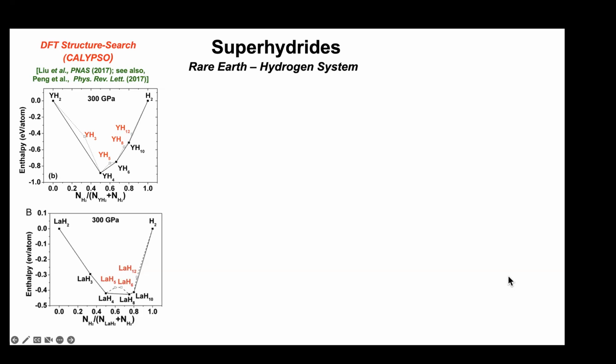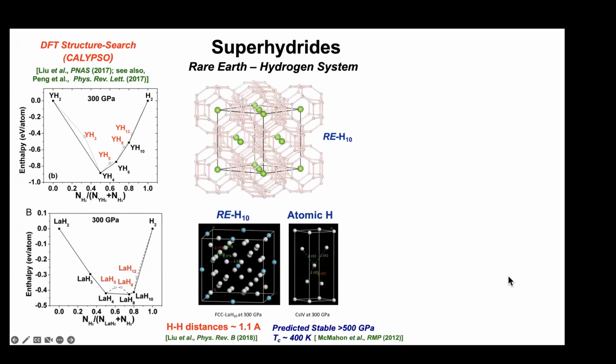And what one finds in these calculations is very intriguing: very hydrogen-rich materials that we called superhydrides, that is, with hydrogen stoichiometries greater than 6, so stoichiometries of up to 1 to 12 in these systems. These are also interesting systems because in the case of the decahydride, of course, it has a very close similarity in terms of local bonding and topology to atomic metallic hydrogen extrapolated back to lower pressures, that is, in terms of the H-H distances and the coordination. So this in fact looks very much, in the calculations, like atomic metallic hydrogen, a doped atomic metallic hydrogen.